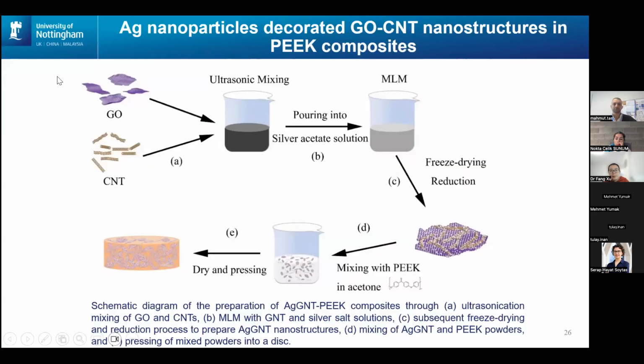So this is how we prepare the composite. Up to here, we have already introduced how we get silver nanoparticle coated GNT nanostructures. We then mix these nanostructures with PEEK in acetone, disperse them together, dry them, and press them into a pellet.